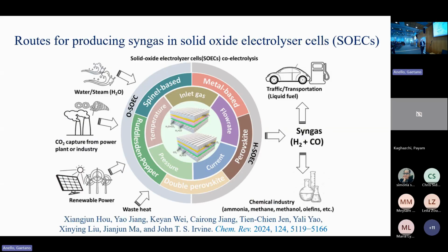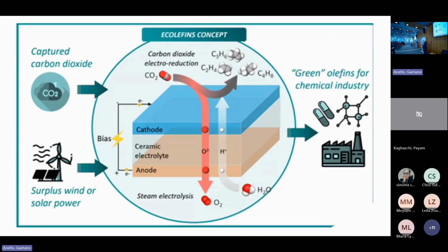Then you can take solid oxide electrolysis and use that for co-electrolysis. You can produce syngas, carbon monoxide and hydrogen, at high temperatures. Then you can convert that into chemicals or fuels. So within ecolefins, we're looking at what would be a clever modification. Rather than having a proton conductor or an oxide conductor, we're looking to have both. Mechanistically, that means you can pull oxygen away from the zone, and you can feed hydrogen into it. So electrochemically you can modify the catalysis. If we can do this, and it's quite a challenge, it's got huge potential, and we're targeting ecolefins.